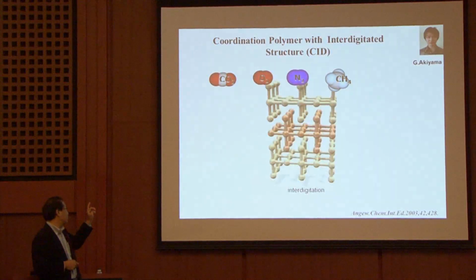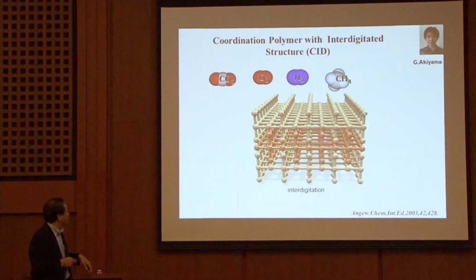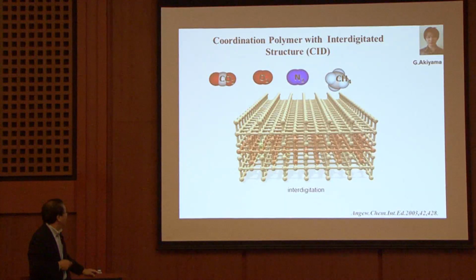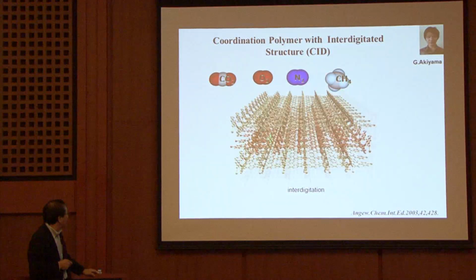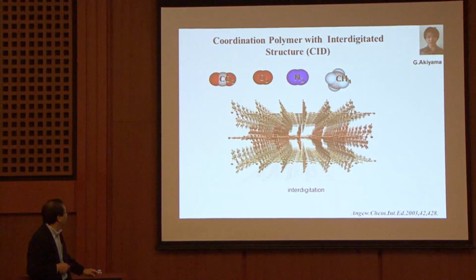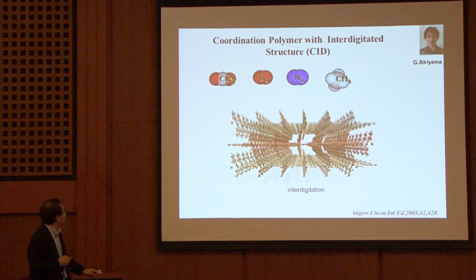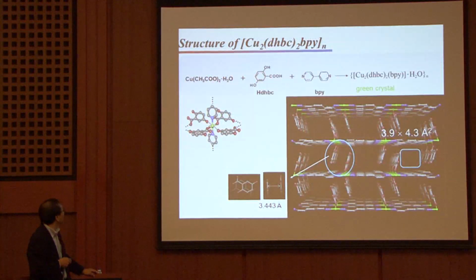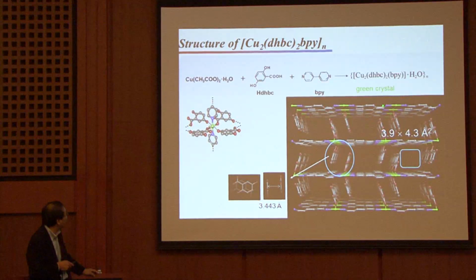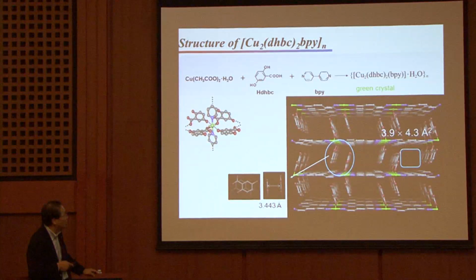Another thing, just as I showed you before, this is the layered system. And the reality is like this, for this kind of gas. The structure is synthesized by copper and dihydroxybenzoic acid and bipyridine. Copper and this ligand give a layer, the pyridine gives a pillar ligand. But there is no strong interaction, I mean, no covalent bond.